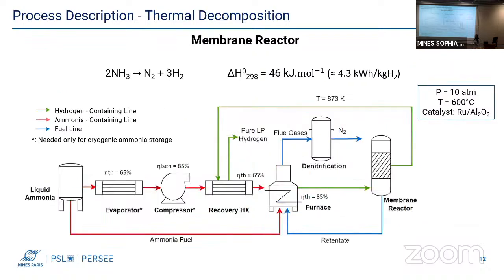In a membrane reactor technology, the fixed bed is replaced by a membrane reactor where the reaction and the purification section take place at the same time. This reactor operates at a pressure of 10 atmospheres ensured by the compressor, at a maximum temperature of 600 degrees C, after which the materials of the membrane start to degrade, and in the presence of a commercially available ruthenium-based catalyst. Heat integration was used in order to provide the energy requirement of the system. Only in the case where ammonia is stored in the refrigerated form, an evaporator is added before the compressor inlet.